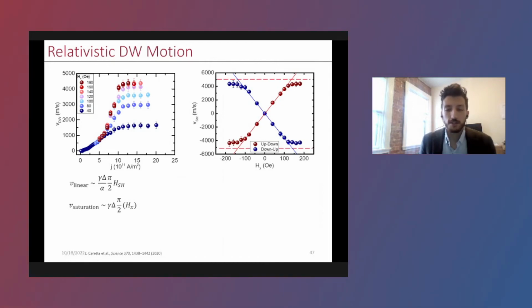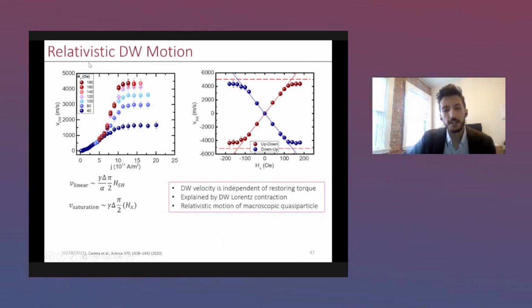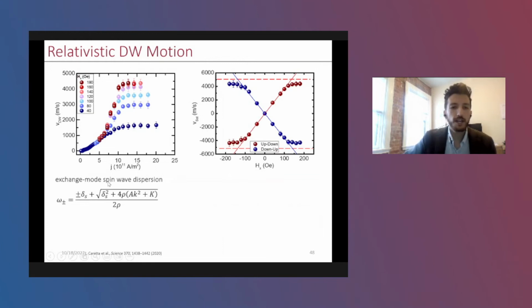And so what we find is that this couldn't be explained by any existing model of domain dynamics, but could quite easily be explained by the Lorentz contraction of the domain. So this velocity is actually independent of the restoring torque. No matter how stiff we make the domain wall, no matter how hard we drive it, the domain wall won't go any faster. And so one can actually calculate the dispersion relationship for this material system. There are no fitting parameters here. These are all experimentally measured parameters. And if you take the derivative of this, you get the group spin wave velocity. That's around 5,000 meters per second, which is quite close to what we see, within 10% of what we see experimentally.